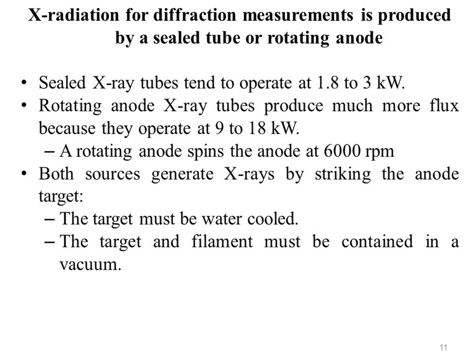X-ray radiation for diffraction measurements is produced by a sealed tube or rotating anode. Sealed X-ray tubes tend to operate at 1.8 to 3 kilowatt. Rotating anode X-ray tubes produce much more flux because they operate at 9 to 18